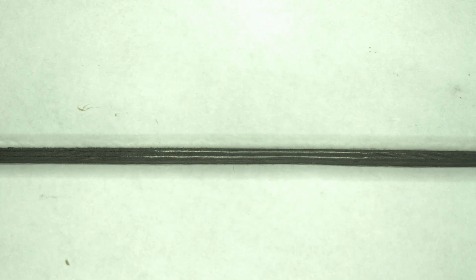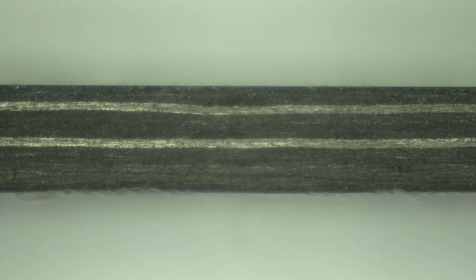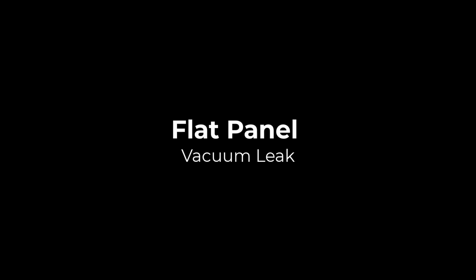After removing the part from the tool, we can see that there are no visible surface defects such as porosity, waviness, or wrinkles. A cross-section of the part shows good consolidation with no voids visible to the eye and minimal voids under the microscope. Flat panel layup, vacuum leak.